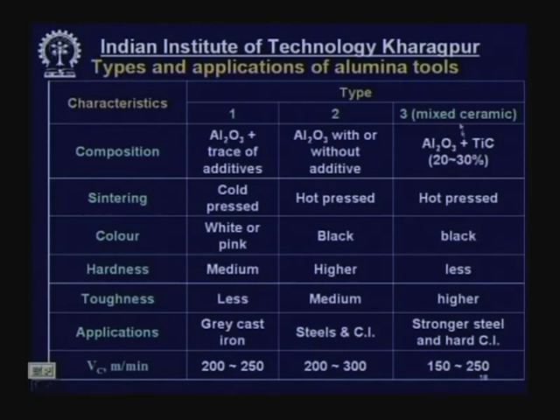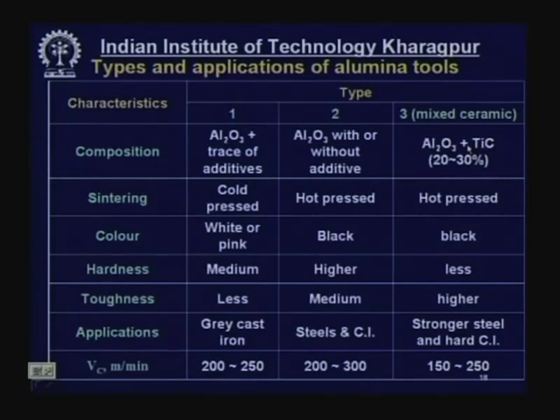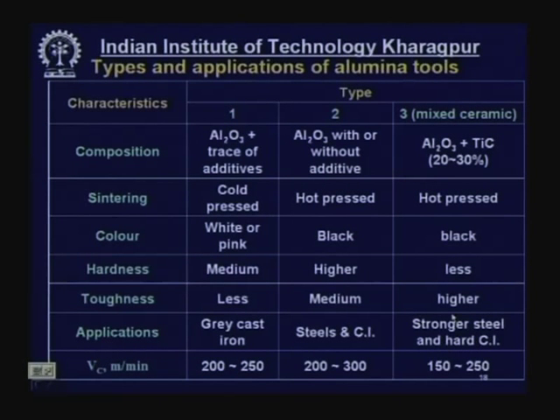Type 3 is a mixed ceramic: alumina mixed with 20–30% titanium carbide, titanium nitride, or titanium carbonitride, which imparts toughness to alumina. It is produced by hot pressing — a costly process — and is also black in color. Toughness is high due to titanium carbide, while hardness is slightly lower. Application is stronger steels and hard cast iron where forces fluctuate; cutting velocity is 150–250 meters per minute.